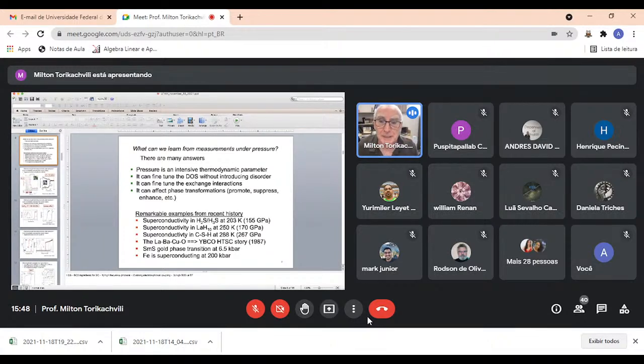For example, superconductivity in this mixture of hydrogen 2 sulfur, hydrogen 3 sulfur, that's the stuff that smells bad. But superconductivity was found at 203 Kelvin under this enormous pressure of 155 gigapascal. This is like 1,550,000 atmospheric pressures. It's a pressure comparable to something very close to the core of the Earth.